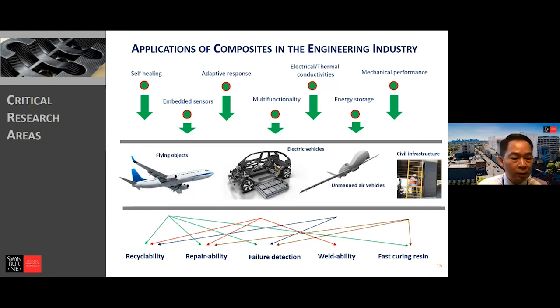Number one is how we can recycle composite material. This is a major hurdle that resists the industry using composite material. How to repair the composite? Remember, I mentioned the repair: the curing time for the resin is about 24 hours. An aircraft is not allowed to sit on the ground for more than 24 hours just to repair a patch. We have only a few minutes to finish the whole repair process and the aircraft has to go, because when the aircraft is landing on the runway, they lose money. The aircraft only earns money in the air. So how we can develop a good repair scheme for the existing composite aircraft, that is key.